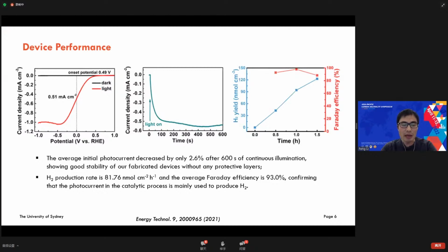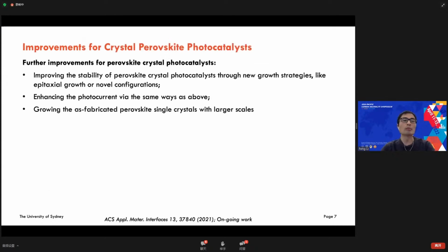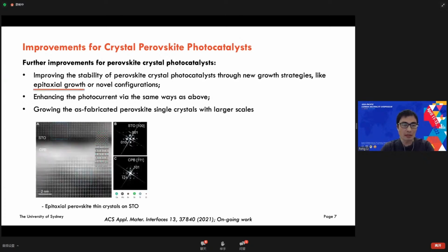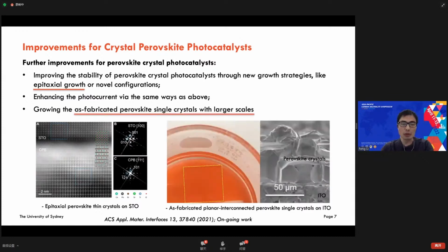As compared to other kinds of photocatalysts, it's not bad, but there's still room to improve the single crystal perovskite photocatalyst. So we currently try to fabricate, using the solution epitaxial growth method, because we want to improve the stability of the device, and also try to fabricate planar interconnected perovskite single crystal on the ITO substrate. This one will have a large area, and we hope that we can get improved device performance.